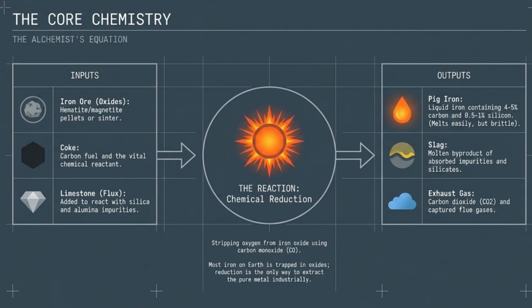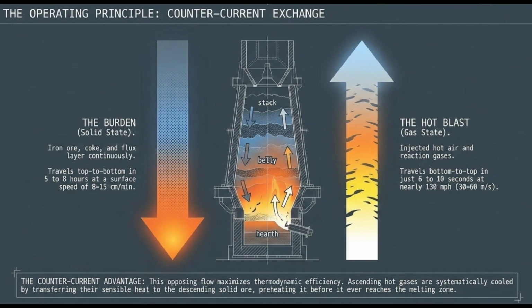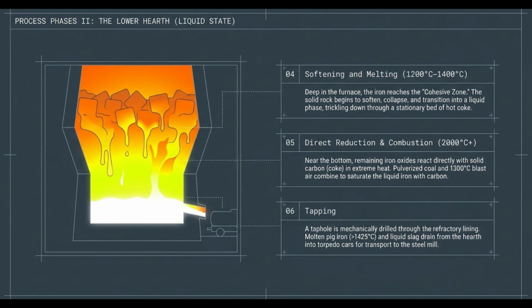Now here is the detail that stops most people cold. The solid materials take 5 to 8 hours to travel from top to bottom. The gases traveling in the opposite direction make that same journey in 6 to 10 seconds. And those gases are not drifting upward. They move at 30 to 60 meters per second, nearly 130 miles per hour, a hurricane-force wind driving upward through a column of solid rock that is simultaneously sinking under its own weight.